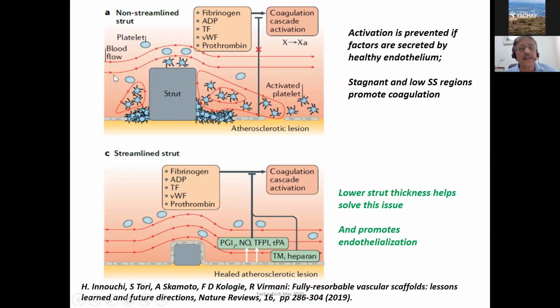Okay, so the thicker strut also leads to disruptions of blood flow, as can be seen here, and creates stagnant regions of blood flow, which then lead to a series of activations of platelets that cause clotting and so on. Okay, so there's a coagulation cascade activation because of the presence of these platelets in the stagnant regions of flow. If you can make the struts thinner, the stagnant regions disappear, so you don't have this coagulation cascade, and there is no more delayed thrombosis, or there is actually a development of healthy endothelial cell coverage if the struts are much thinner, in the region of 80 to 100 microns.